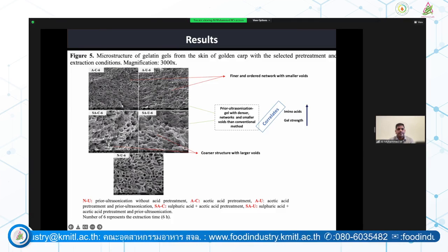Similarly, the acetic acid treated without ultrasound showed very small pores with an increased number of pores, indicating that there were higher crosslinks happening between the polymers. And the ultrasound treated gels showed a very fine, very unique pattern of cross-linking. These gels showed good water holding capacity, good chewing capacity, etc. So based on these observations, we could see that ultrasound does more than increase extraction yield. It can also improve the quality of the gelatin extracted and of the gels formed, with smaller pores, which will have good textural properties when we apply them in food science.